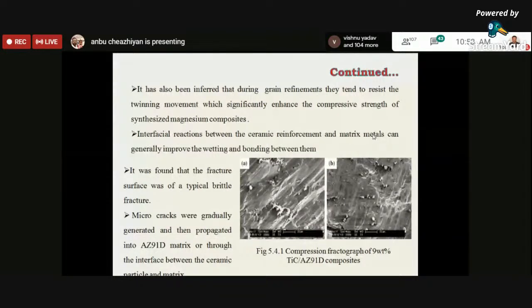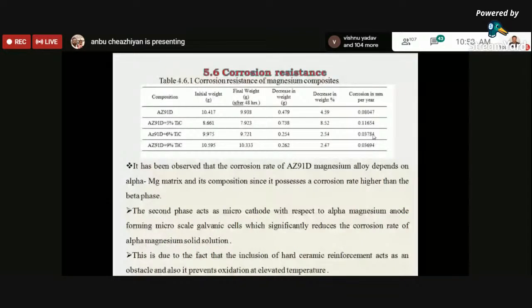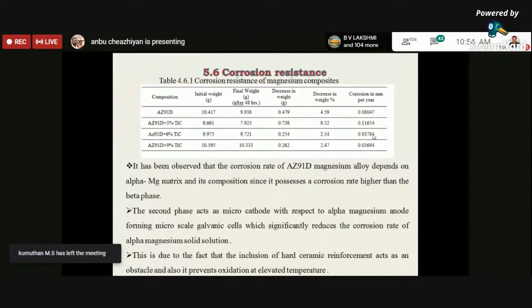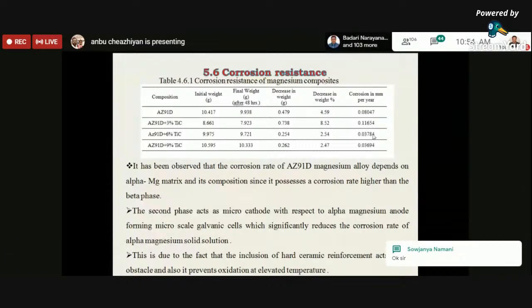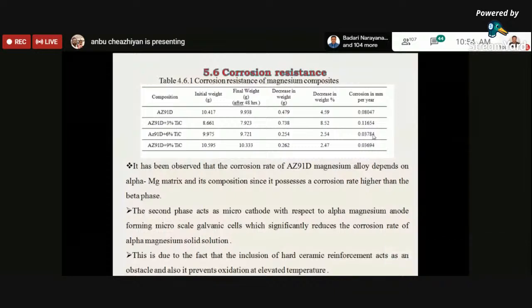So this is the corrosion resistance of titanium carbide reinforced magnesium composites. The corrosion rate of AZ91D magnesium alloy depends on the alpha magnesium phase and its composition, since it possesses a corrosion rate higher than the beta phase. The second phase acts as a micro cathode.